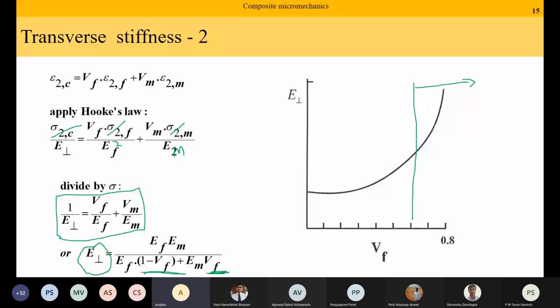I mean, if I had, let us say 20% and if I have 30% fiber, I am increasing the fiber content by 1.5 times, but the modulus increase is only going to be 5 or 10%. On the other hand, after some critical value of volume fraction of fiber, even a small amount of fibers will increase my modulus to a very high value. Okay. But now we have another problem. Do you think that I can make a composite with 95% fibers? Is it possible?